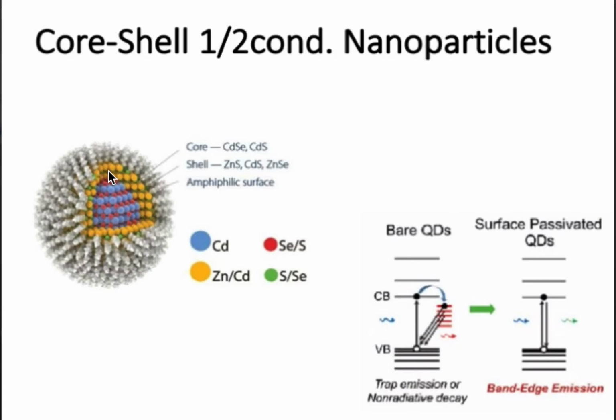It is to passivate the surface, and it is illustrated to the right. One wants the electron-hole pair to recombine within the core. There will be surface states on the surface that might give non-radiative recombination and not emission of the right color. The shell makes most of their wave functions stay in the core.